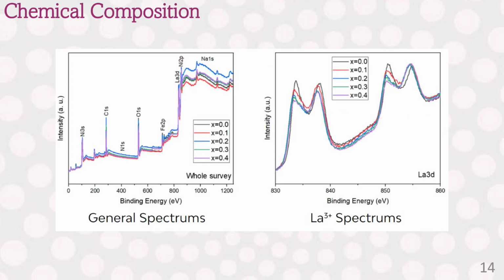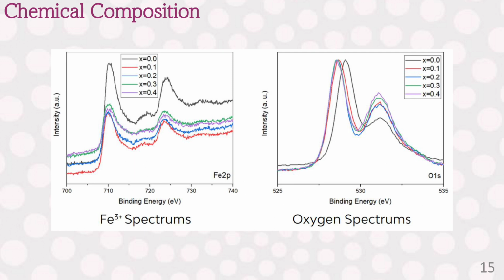The XPS characterization allowed us to know the chemical composition of the samples. The general spectrum and those of the elements lanthanum, iron, and oxygen are shown. In the oxygen spectrum there are peaks characteristic of the oxygen contribution of the lattice and of the vacancies in the same lattice. In the iron spectrum there are the peaks corresponding to Fe 2p that refer to the iron 3+ states, and finally the characteristic multiplets of trivalent lanthanum that corresponds to ferrite, that is to say, the chemical composition proves the presence of lanthanum ferrite.